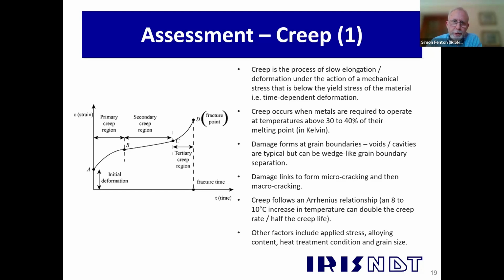So there's a progression that you start off with cavities, and the next slide will illustrate this for you quite well. We start off with cavities, which then link to form micro cracks, and then the micro cracks form macro cracks. And this is the progression around the creep curve on the left there.